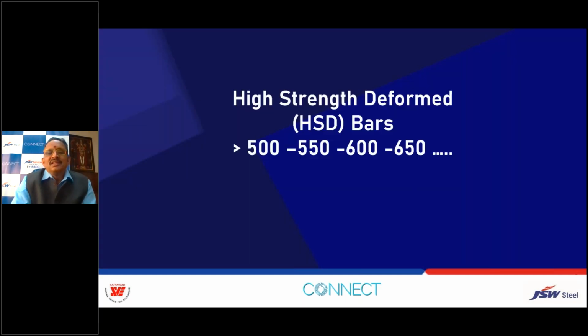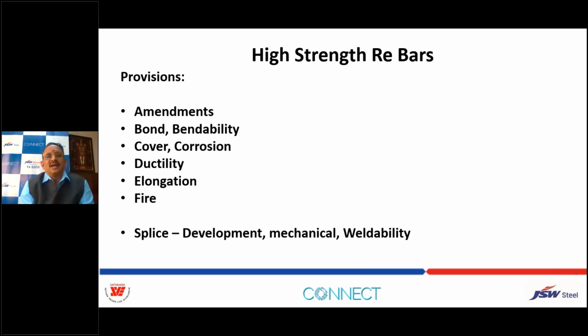And now let us talk about high strength deformed bars, which is ranging beyond 500. And now we are talking about 550. And in India also we have possibility of procuring 600 or 650 also customized. So we can procure if the particular project requires this kind of high strength. And there are provisions, as I said, in ACI. So the provisions that are required for high strength rebars in the codal provision, amendments are required for IS 456. As I said, it requires the improvements in the bond and the bendability of these high strength bars.